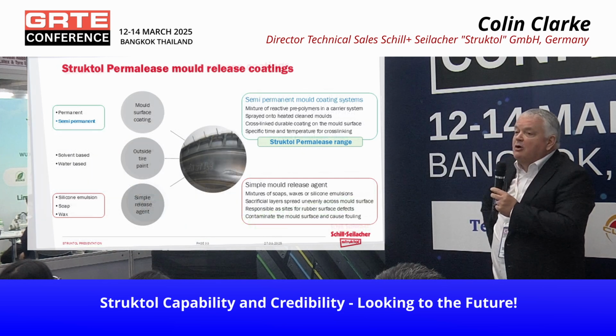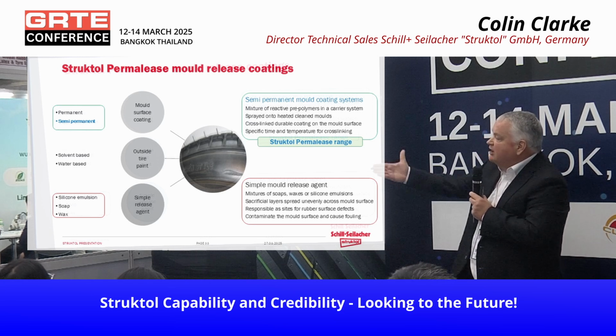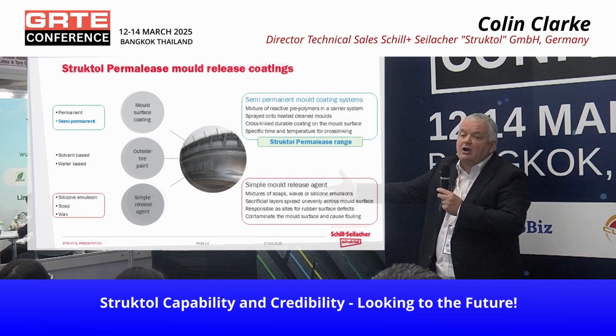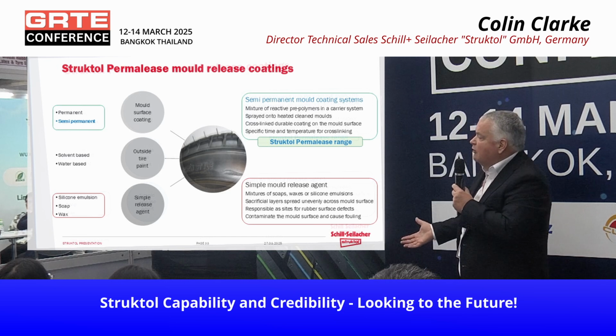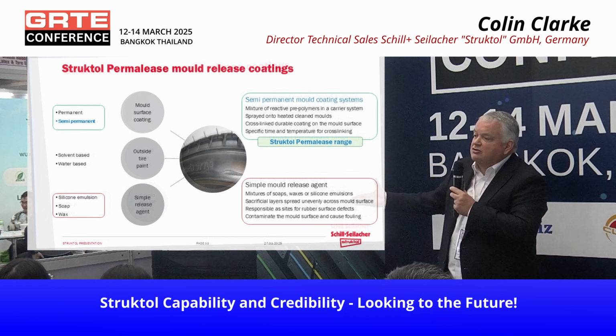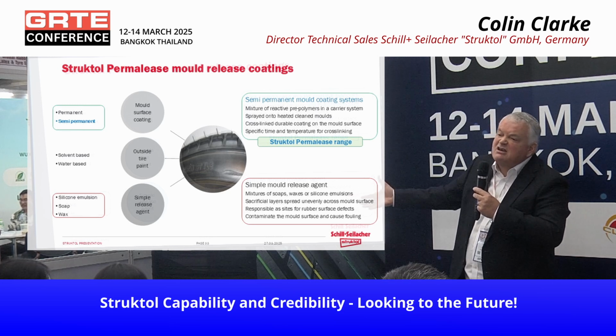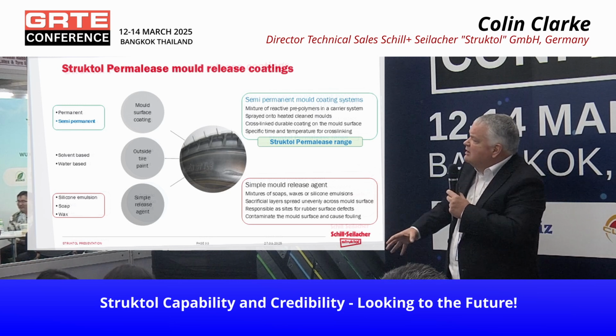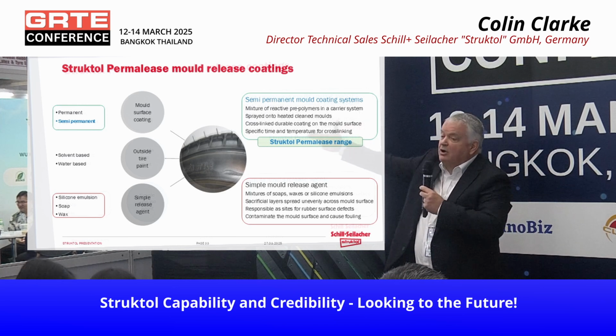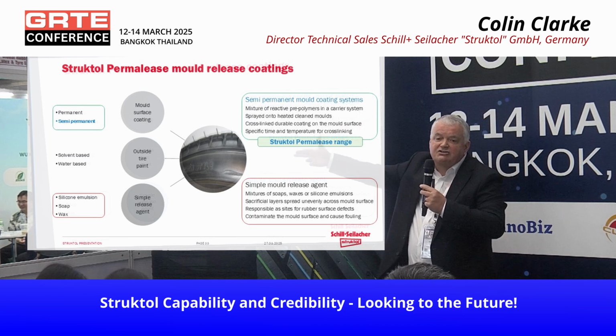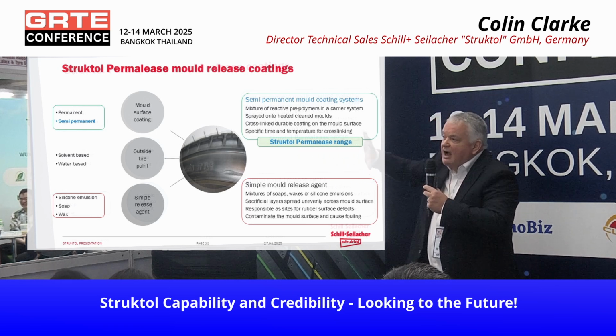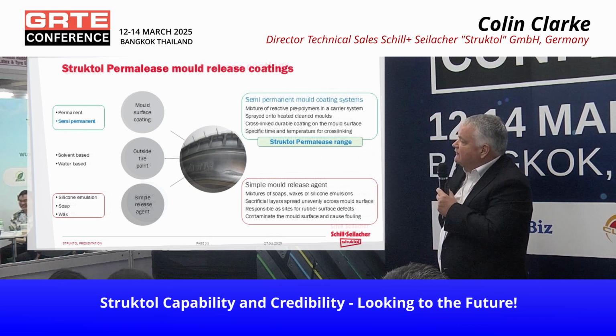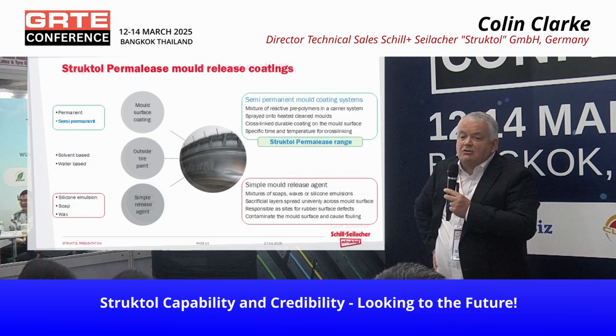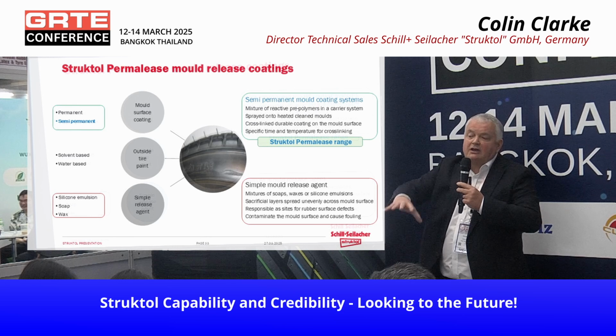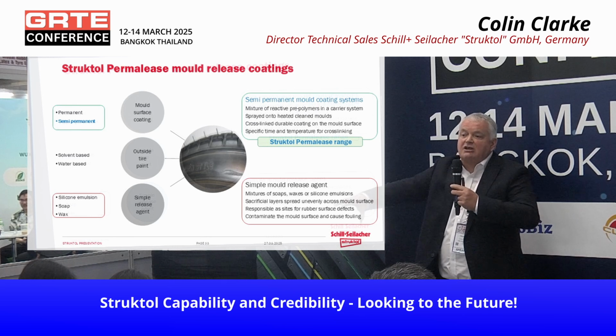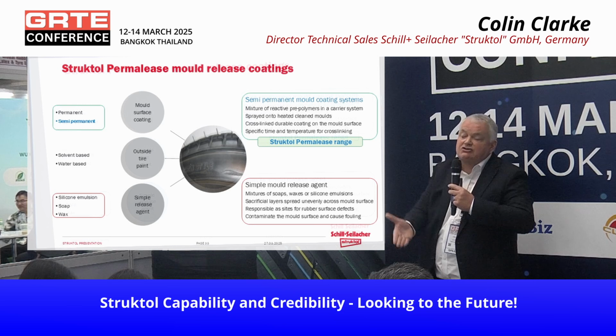So mold release, there are plenty of mold releases on the market. You'll find very simple silicone emulsions, soaps, waxes, all kinds of materials applied on the surface of the mold. But a lot of those release agents cause damage to the mold, they cause mold fouling, they really need to be applied at every cycle. On the high end, you can find permanent coatings, so people coat their molds with chromium plating or maybe with some special reactive vapor deposition technologies onto the surface. But we work with semi-permanent coatings. These are coatings that are applied to a mold, they cross-link, and they form a long-lasting coating that can be used for many moldings before it needs to be reapplied.